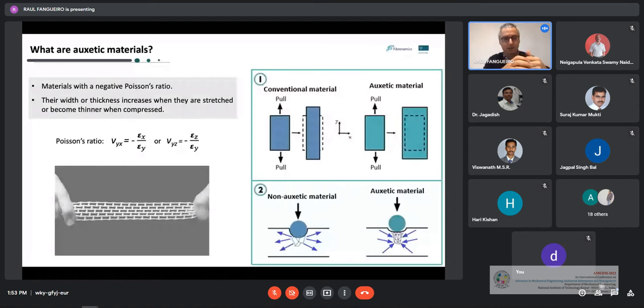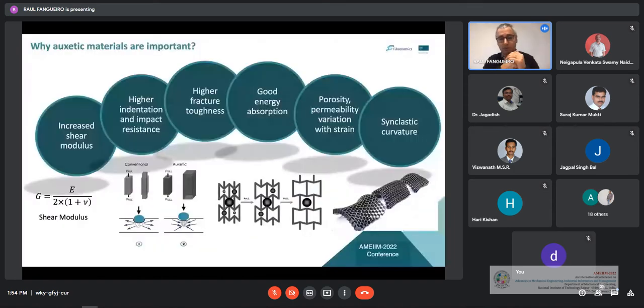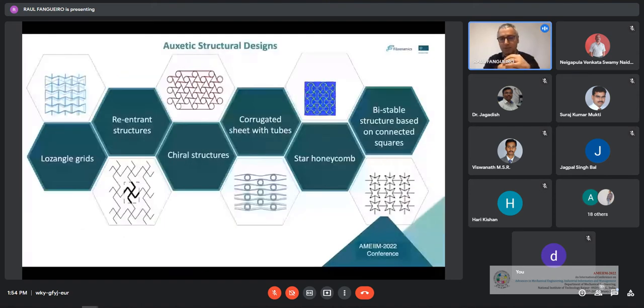So we are increasing the shear modulus, we have higher indentation and impact resistance, higher fracture toughness, good energy absorption, and porosity and permeability variation with strain, as we are imposing strain in both directions at the same time, and we have a synclastic curvature on the material. This is quite important for applications in terms of energy absorption and impact resistance, and that's why this type of strange, non-conventional behavior of materials is being quite explored for these impact applications.